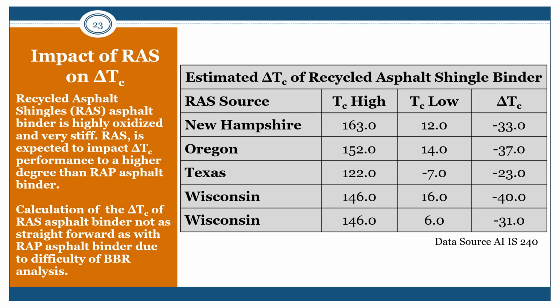Calculation of delta TC of RAS asphalt binder is not as straightforward as with RAP asphalt binder due to RAS binder stiffness. This highlights some of the issues with delta TC. Extraction and recovery commingles the RAS and the virgin binder, whereas this does not occur at the same extent in the field. You can notice that these numbers for delta TC are quite wide for the RAS binders, and the reason for this is that the T sub C temperature is much higher than we would see on an asphalt binder used in paving. These numbers are typically in the negatives for asphalt paving binders for both the T sub C high and the T sub C low.